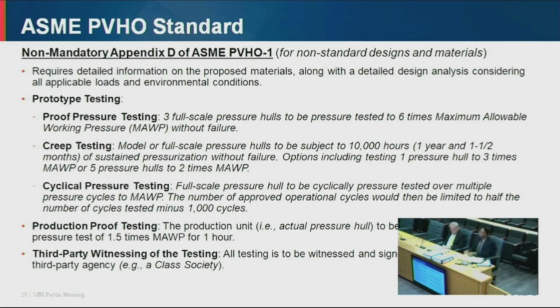So under creep testing, what is creep? Creep basically means, under sustained hydrostatic loading, does the pressure hull deform? Okay, that is creep. For creep testing, you will use model or full-scale pressure hulls, and they are subjected to 10,000 hours of sustained pressurization without failure. 10,000 hours basically means 1 year and 1.5 months. So you will pressurize the hull and maintain the pressure for 1 year and 1.5 months, and then you check if the hull has deformed or has failed by creep. Okay, so the options available include you test 1 pressure hull to 3 times MAWP, or you test 5 pressure hulls to 2 times MAWP.